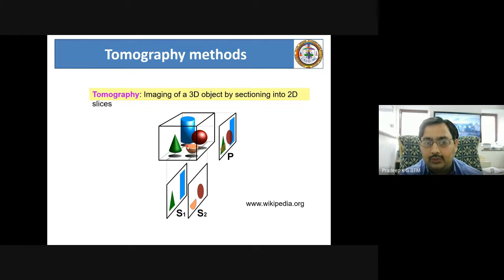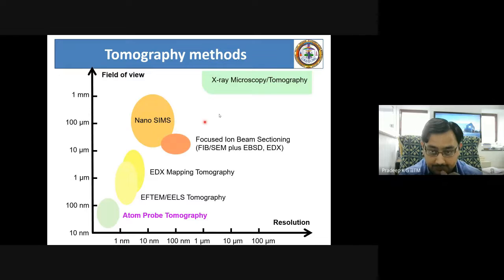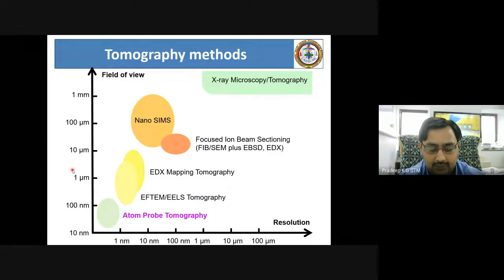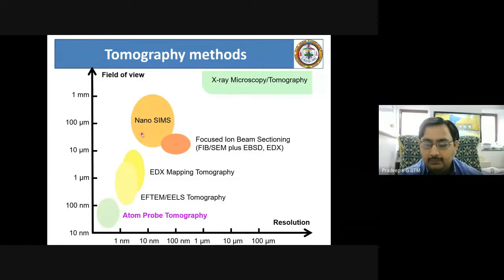So therefore, there are tomographic techniques that have been developed over the years, starting on a coarser scale with X-ray microscopy, where you can have a large field of view of a millimeter and even more, with a resolution in the range of 100 micrometers. But if you want to study nanoscale features in their three-dimensional shape, then these techniques may not be sufficient. Therefore, you have to come down in resolution. And as we come down in resolution, the field of view naturally decreases because we are going into higher and higher magnifications to get the information. At the same time, we are getting better and better resolution, or more detailed information, using this kind of comparative chart.